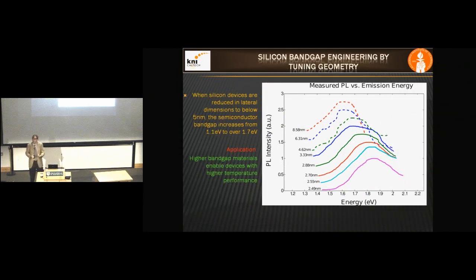And these smaller structures behave differently. If you look at them by doing photoluminescence, you actually can see that the energy of the luminescence is going up as you shrink the device. So if you go from 8 nanometers to 2.5 nanometers, you see this shift of the band of the luminescence. But wait, silicon shouldn't be luminescing because it's an indirect bandgap semiconductor. It turns out that you've changed the band structure.